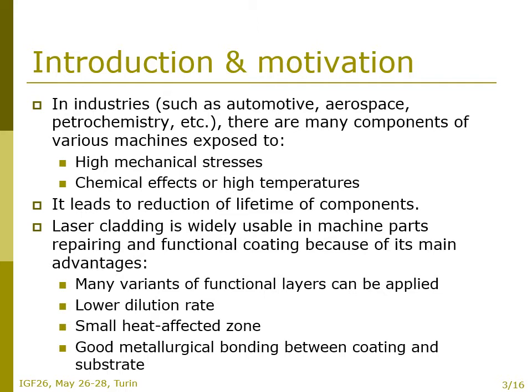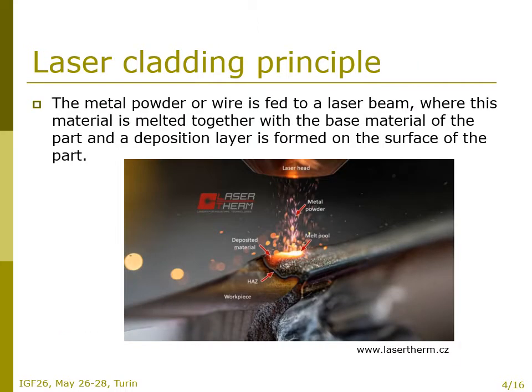Many variants of functional layers can be applied, with a lower dilution rate, small heat-affected zone, and good metallurgical bonding between coating and substrate. The basic principle of laser cladding can be seen in the figure, where the metal powder or wire is fed to a laser beam, where this material is melted together with the base material of the part, and a deposition layer is formed on the surface of the part.